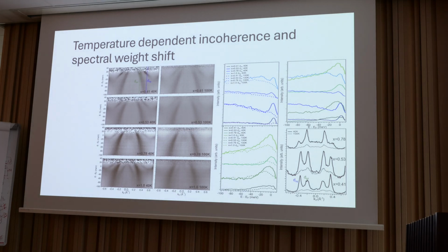We also do temperature-dependent studies, and we see that as we increase doping, the dxy band is selectively lowered in spectral weight, and even at the same temperature there's a difference in the coherence level. As you can see here, this dxy peak gets broader and broader at 40 Kelvin, and the dotted line is 100 Kelvin, where it's no longer resolvable at 78% doping.